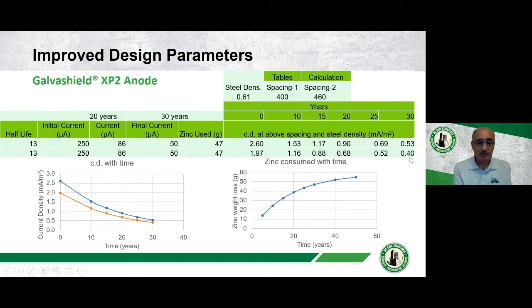So working that out in our spreadsheet, we get a spacing of 460 millimeters, which is a little bit better, if you like. If you want to save anodes, it's less anodes for your structure. And this is the current distribution that's worked out from there. But what it does, it gives you more confidence that, I mean, initially this was not guesswork, but you couldn't really predict what would happen in the future. We now know, so we'll work from the future backwards. We'll design what our current density should be at 30 years, or 20 years, or 10 years, or however long you require your anode to be running, and work backwards to state what your initial current should be.